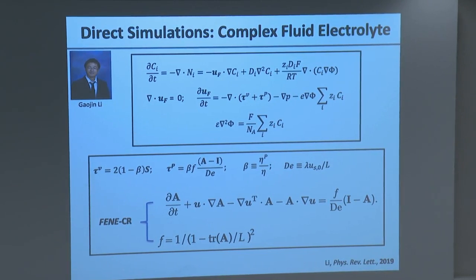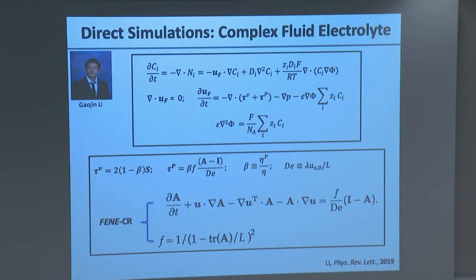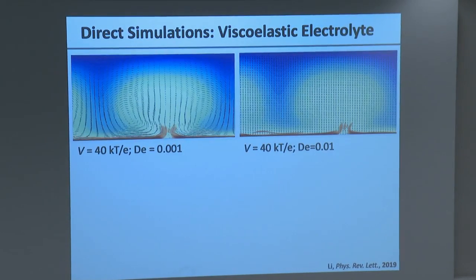But instead of using that roly-poly polymer model, we use a polymer model called the FENE-CR model that is actually more amenable to very straightforward numerical simulations. And what is nice here is that we can now simulate the whole system, including the polymer stresses, to see what's going on, when it's happening, so we can learn what the mechanism is by which the polymer is producing stability. And so perhaps we can understand why it's so effective across different types of chemistries. All right? So the results are kind of cool.